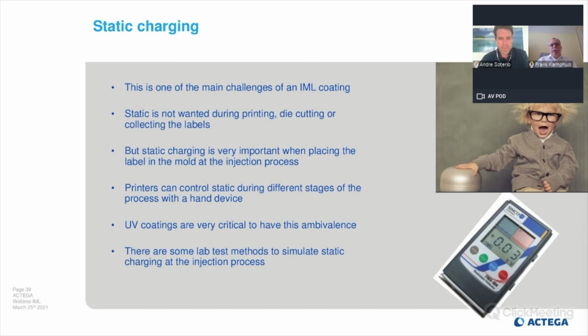Then static charging. I would say that is the most important topic for the label and the coating. In every case, if you are using the wrong coating, then you are lost, because you can't repair this issue. So the first thing is that you are really using the right IML coating, because in quality control it should be checked that the charging is in the right range.